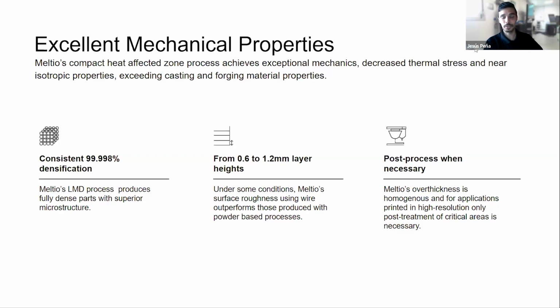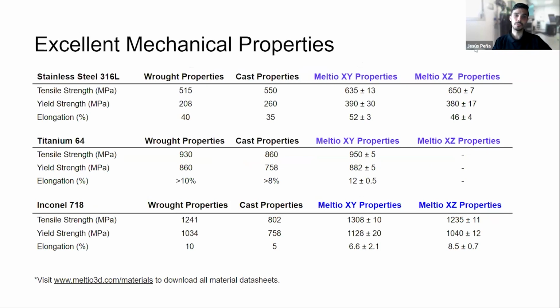We have a material handbook where we are already giving several recommendations of how to perform all those processes, just to make the life of the customer easier. And this is an example of the material properties we are able to get. As you can see, if you compare the Meltio as-printed properties with wrought and casting, in the example of the stainless steel, we are getting better properties than with the regular processes followed in the industry. With titanium, you can also see what we are able to achieve when printing with our system and processing the materials with the recommendations in our materials handbook. Same for the Inconel.